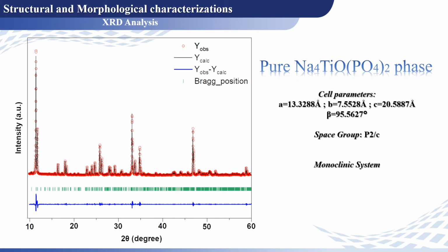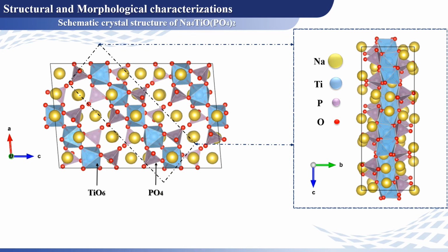Now let's move to the structural characterization of our material. The XRD analysis shows a pure and well-crystallized material which can be indexed into a monoclinic system with P2/c space group and the following cell parameters. As we can see here, the structure of the sodium titanium phosphate consists of the arrangement of titanium oxygen octahedra sharing oxygen and linked 2 by 2 by phosphorus oxygen tetrahedra to form chains, and the sodium ions are located